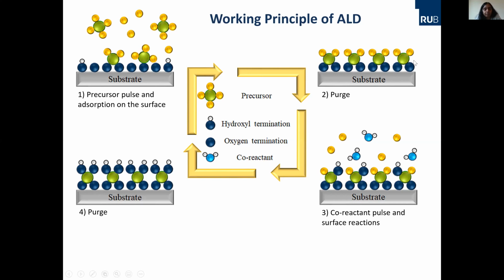Now you want to make hafnium oxide, for example. So you take the hafnium chloride precursor. Then as the oxygen source, you can use water as a co-reactant. So in the next step, once this adsorption is finished here, you introduce water. So this blue little molecule here will react with the two other chlorines here. And again, HCl is released, and you have a hafnium oxygen bond formed.